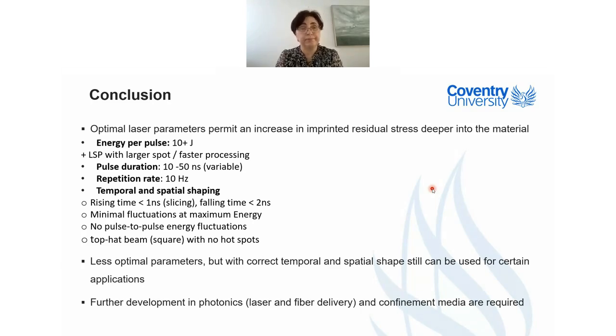So in conclusion, I would like to say that you need to think about the optimum parameters of the laser you should use. In this regime, it's good to have 10 plus Joules, because that allows you to play with the spot size and also allows a faster process. Pulse duration is very important because, as you see, it defines how deep you can go in the material. Repetition rate, we were using 10 hertz, and as you see, that was not a limiting factor in the speed of the processing.